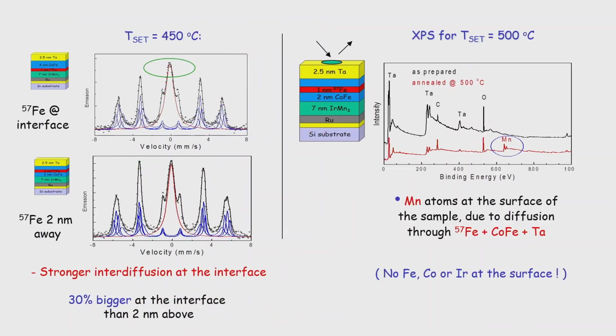And we did also XPS. If you compare the samples with the probe layers at different positions, let's say the interface and 2 nanometers away from the interface, we see that interdiffusion is already 30% bigger at the interface than, let's say, 20 angstroms above, okay? And another interesting thing is that if you do XPS on top of this stack, you see that manganese, this is the biggest interdiffusion, manganese goes all the way through the stack up to the surface. Okay? You'll see that if you measure here, you see a lot of manganese after annealing, okay? This is the manganese that is the guy that is diffusing through the sample.